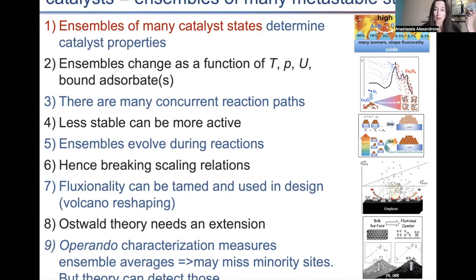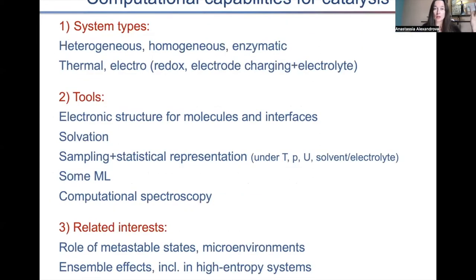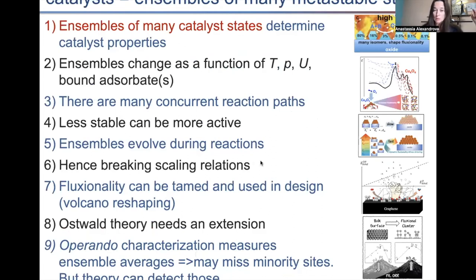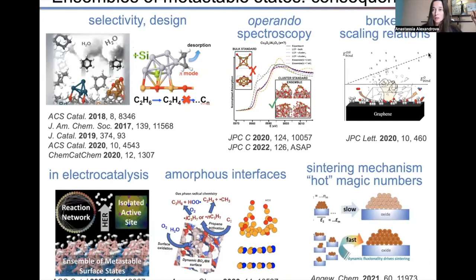My observations: there are catalysts so much in motion under reaction conditions that we have to think of them as ensembles which break all sorts of rules such as scaling relations. Theory will become indispensable for some operando spectroscopists dealing with their spectra. Less stable can be more reactive. Many concurrent reaction pathways have to be considered simultaneously. For this center, perhaps the interest in my work is that we cover a large space of possible systems — heterogeneous, homogeneous, and enzymatic — and draw experience and cross-pollinate among them.